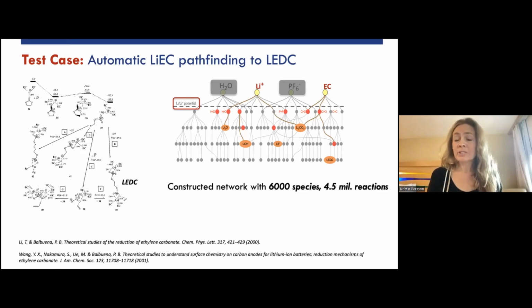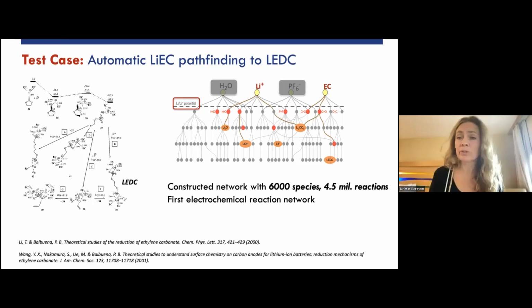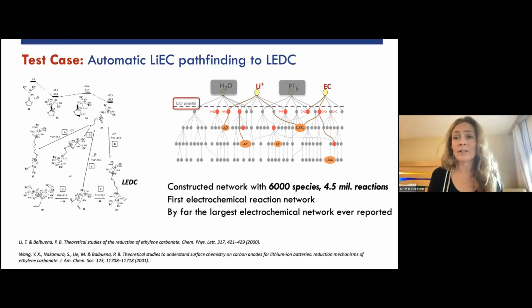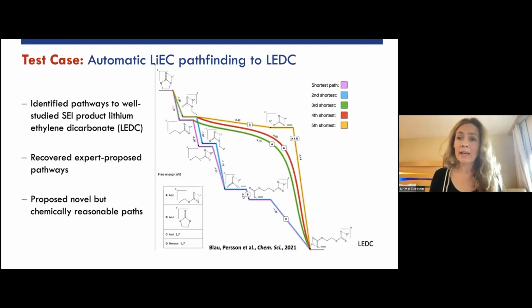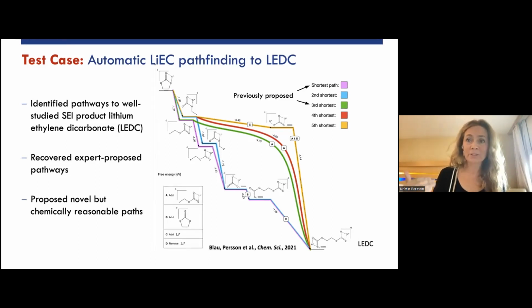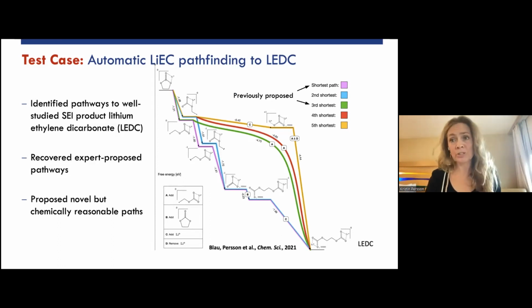So this is a network with 6,000 species and 4.5 million possible reactions. To our knowledge, it is the first electrochemical reaction network and by far the largest. So what did we get? Did we actually form LEDC, as Perla showed beautifully some time ago? And we were very happy to see that indeed her two paths, the double electron reduction and the ring opening, do fall out of our network completely automatically. These are the shortest path by thermodynamics, so the steepest delta G, as well as the third shortest path.